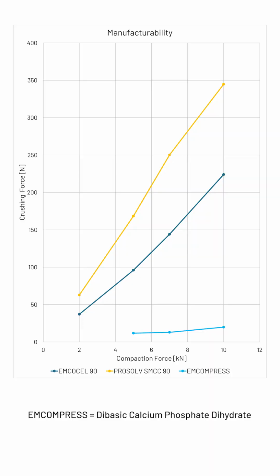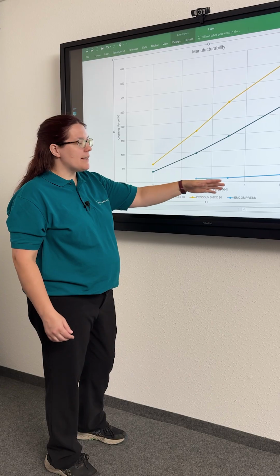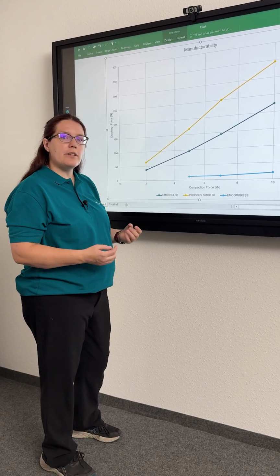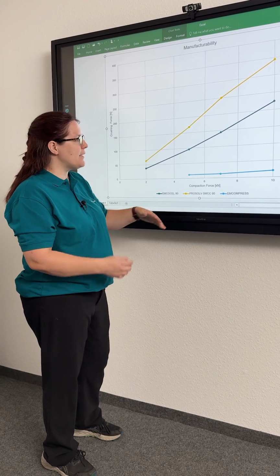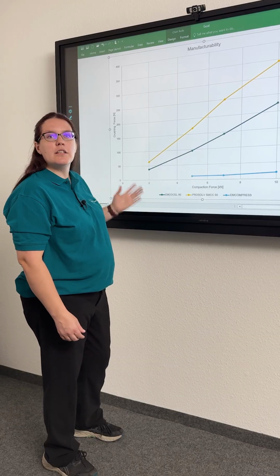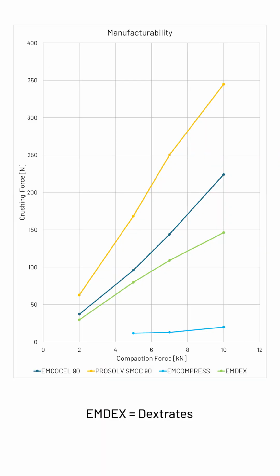And here you can see we refer to EMCOMPRESS as a filler and MCC or SMCC as a filler binder, because here the EMCOMPRESS, it may have helped some flowability because of its high density and flow properties, but it's really not contributing to the tablet hardness. Finally, let's take a look at EMDEX. So this material is actually quite nice. It had excellent flowability, and here you can see that it has a nice response where you can get good tablet hardness as you increase compaction force.